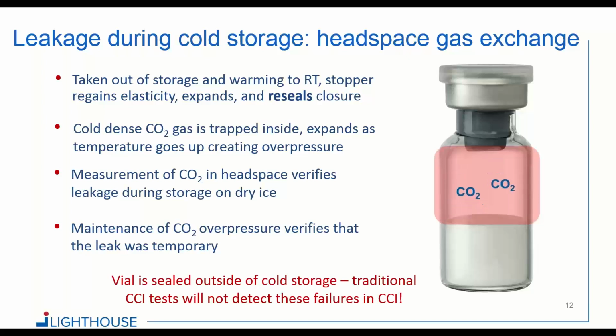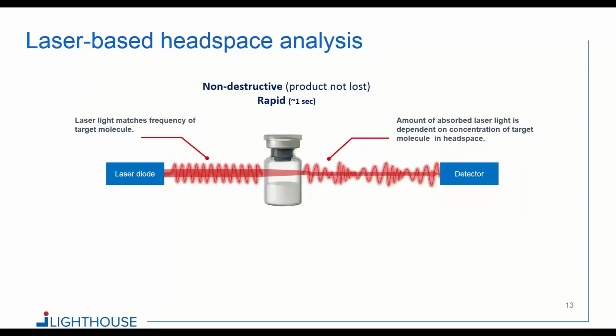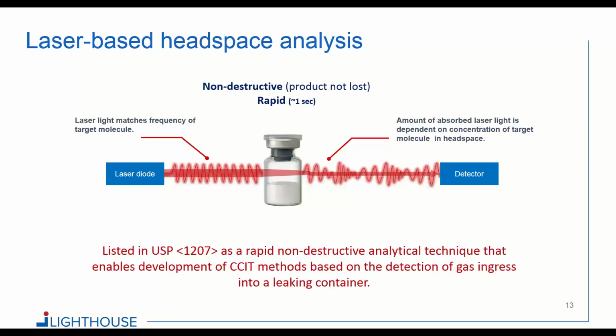Okay, so how would you detect this CO2 gas that has come inside? So here's where laser-based headspace comes in, because it's exactly a technique that allows you to measure and quantify trace amounts of gas inside of a sealed container. And for those of you who are not familiar with the method, it's a spectroscopic method. You shine laser light through the headspace of a container, detect how it's absorbed, and you can actually quantify what the gas conditions are inside of that closed container. And it's a non-destructive measurement, so nothing happens to the sample. It's also rapid, on the order of seconds, so it allows you to generate a lot of data in a straightforward manner. It is listed in the USP 1207 chapter.